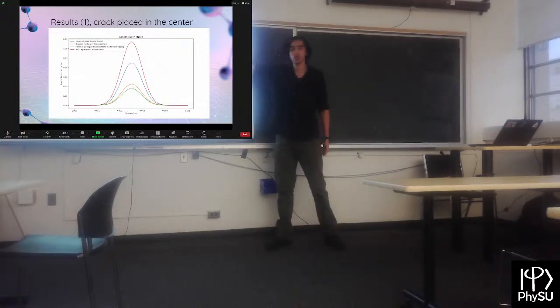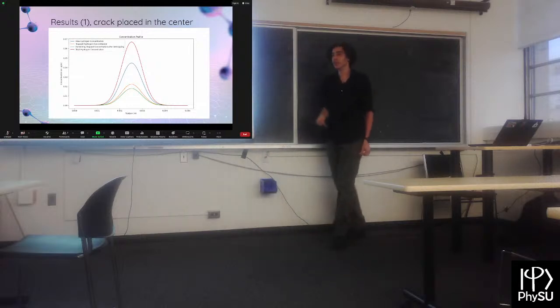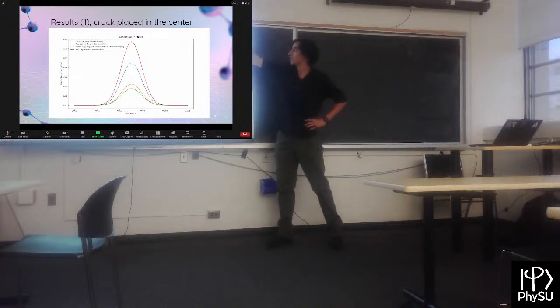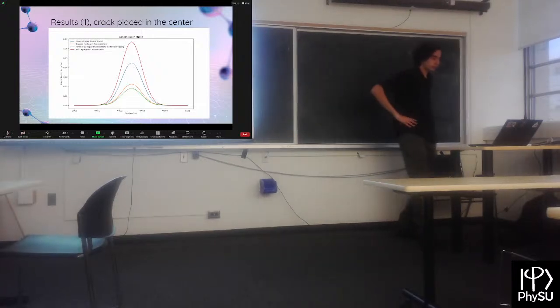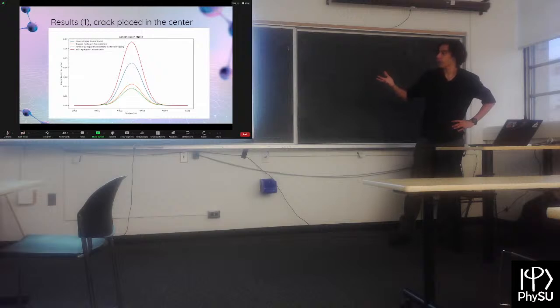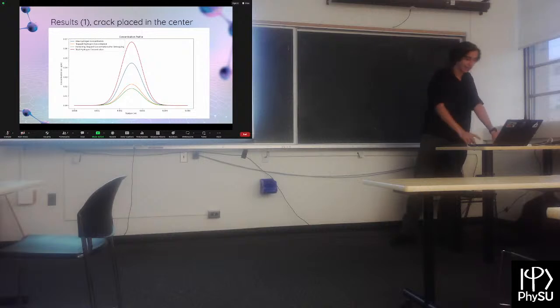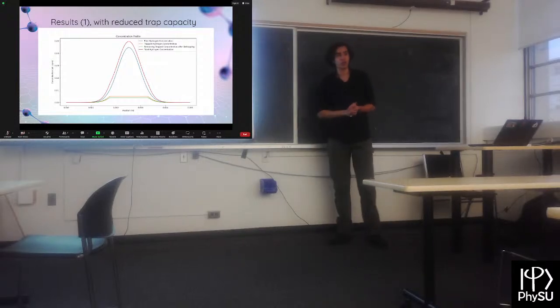As you can see, the red line is the total hydrogen concentration, the blue line is the amount of free hydrogen, and the orange line is how much is trapped within the metal. And the amount of hydrogen in the system, the red line, aligns with the sum of the trapped hydrogen concentration and free hydrogen concentration. So all of these align and verify that the distribution is accurate and the equations are functioning as they are supposed to.